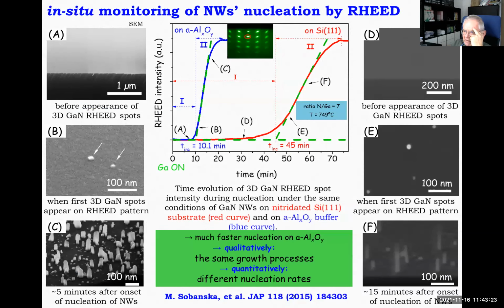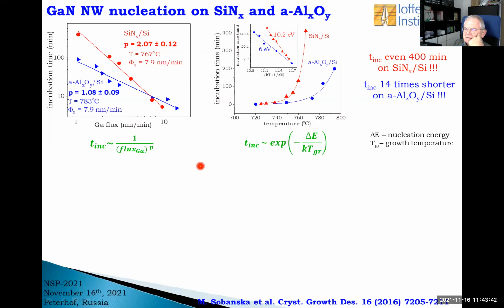What's important for us is that if we make this comparison, you easily see this under the same conditions: growth on silicon nitride and aluminum oxide. As I mentioned, incubation time on aluminum oxide is much shorter. We have studied the dependence of this RHEED-measured incubation time on gallium flux and temperature. So these are on both substrates.